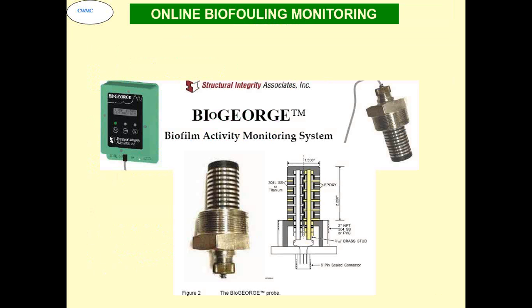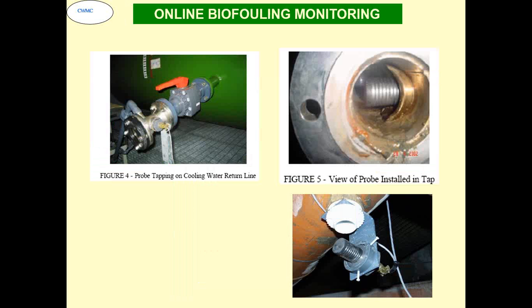Now these are the typical online monitors. This is an electrochemical based online biofouling monitor, which once installed in a system, what you see here are the electrodes. So these are the electrodes and they are at a slightly higher charge. Whenever there is biofouling, first biofouling will occur on this one and you get the change in the current, and because of that you will know there is a biofouling change. So using this system you can optimize your biocide dosing. This can be fitted directly online or can be kept open in the cooling tower also.